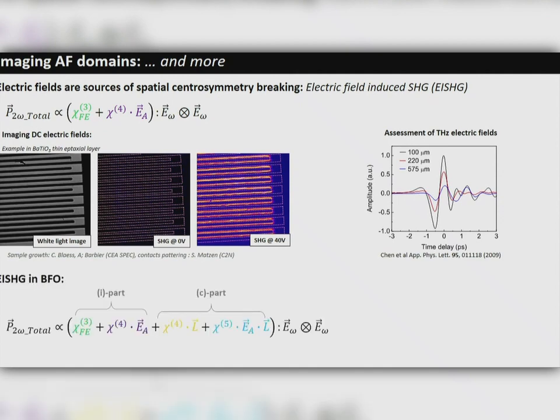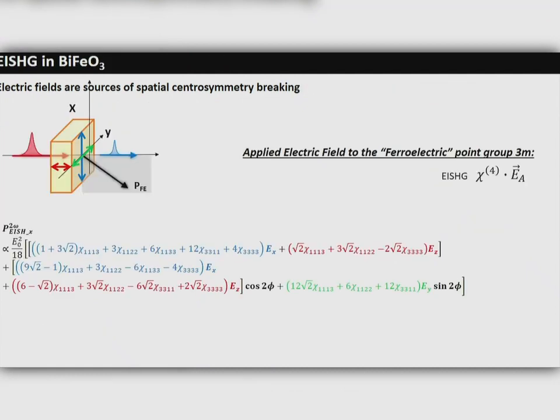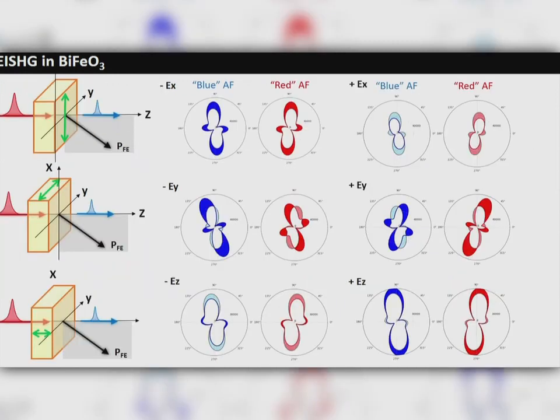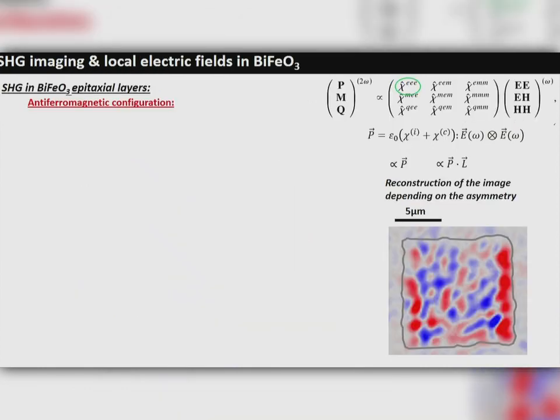So in our BFO, of course, things are becoming a bit more complicated because then we have to add all this antiferromagnetic part. But nonetheless, okay, I will skip this one. But basically, if you do a bit of tensor geometry, you can see in the BFO point group, if you apply an electric field along X, Y, or Z, what's going to be the contribution. And if you do this, you can see that, for example, an electric field along the Y direction will mostly tilt our angular dependence, while some other will change the ratio between the two configurations of incoming polarization, et cetera, et cetera.